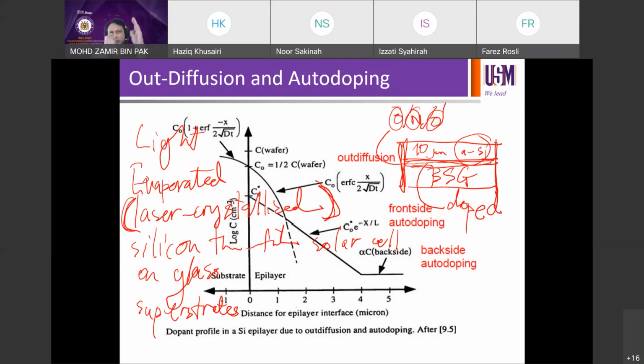Kemudian when you do the laser crystallization, you melt, right? You melt the silicon. So due to the melting process, high temperature lah technically, you don't use the heat from furnace, tapi you pakai laser. So the laser melting will actually cause out diffusion of the dopant from the interlayers. Dia akan out diffuse masuk silicon and dope the silicon.